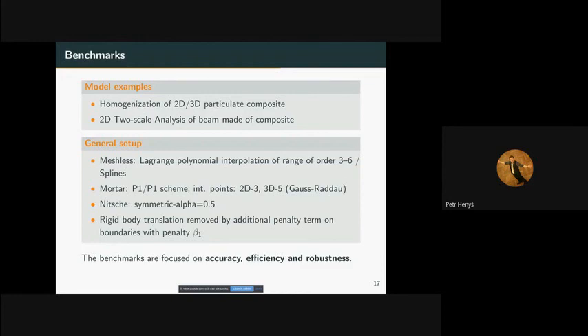In our cases, we found that the most efficient was to choose a penalty to force the mean value of the displacement field being 0. So we control it by another term, by another penalty. What was interesting was that it was almost insensitive to the value, so it was pretty good for us. It was just influencing somehow the condition number, but it was not so significant with respect to the way how to solve the problem. So we use that one.